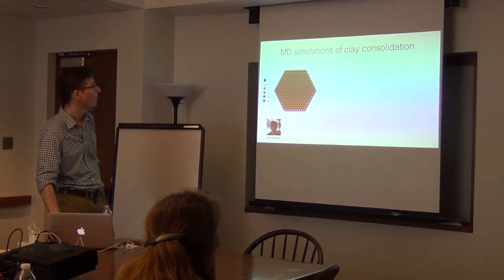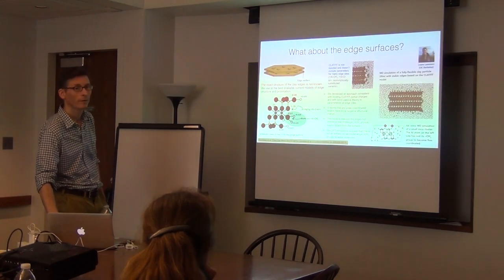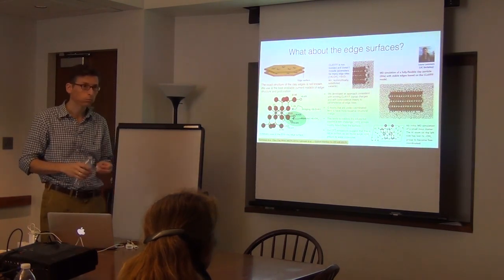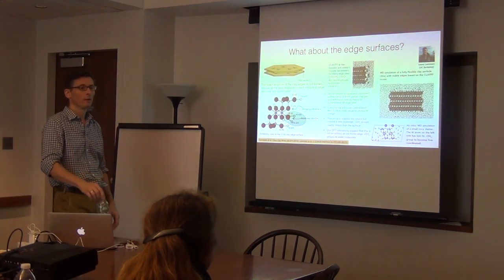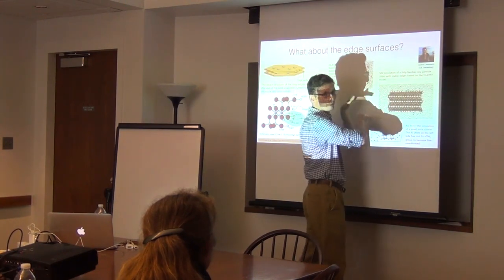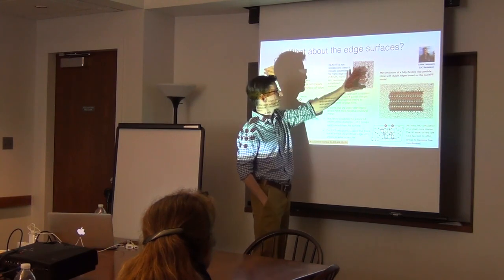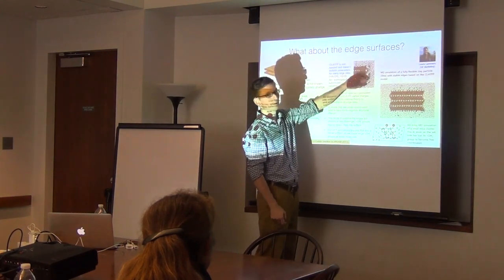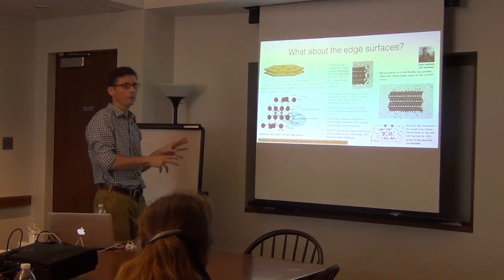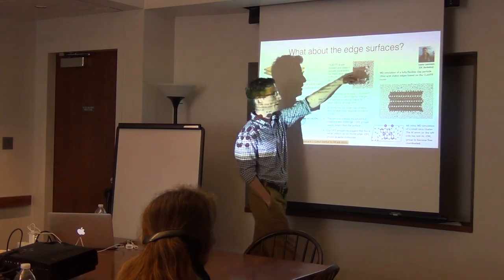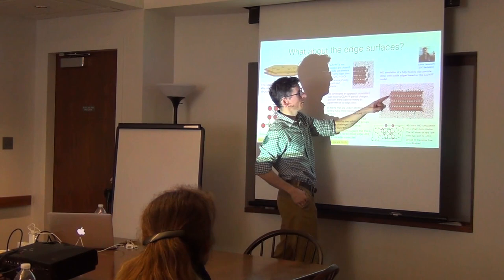Now we can model little mini smectite particles. The reason the 1% edge surface matters is that without being able to model cut edges, we can only model infinite particles going through the periodic boundaries of the simulation box. When previous people tried to just cut the edges with the original force field without fixing the parameters, the particles just break apart — everything explodes. So you can't actually model these particles as fully flexible particles tumbling around in water unless you figure out a way to tweak the parameters to model the flexible edges.